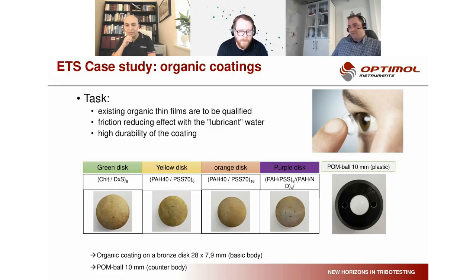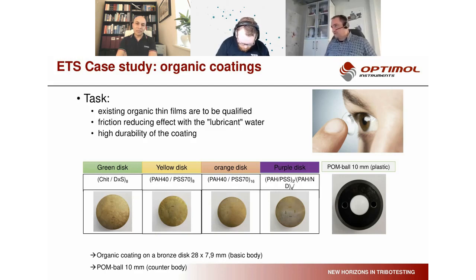Those organic coatings are very thin films. In this case that we had, the target was to coat contact lenses with those organic coatings in terms of producing sustainable contact lenses that you can use several times with a high durability and with very smooth friction properties in order not to get any problems between the eye itself and the contact lens. And therefore we had 4 candidates for organic coatings. All were applied on bronze discs, and the counterpiece was a POM, a plastic ball, and we ran under dry and wet condition with the lubricant water.